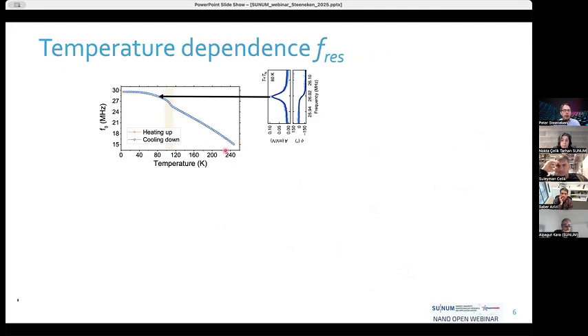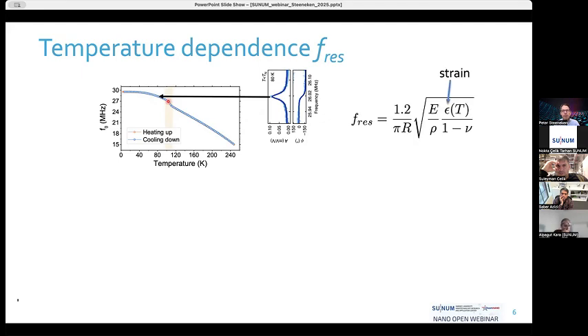So that's what we did here. What we see when we cool down is that this resonance peak is increasing in frequency, but we also see something peculiar here. The slope is steeper around about 114 Kelvin. And we try to understand that.